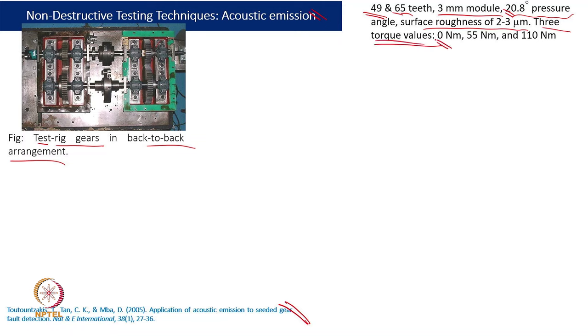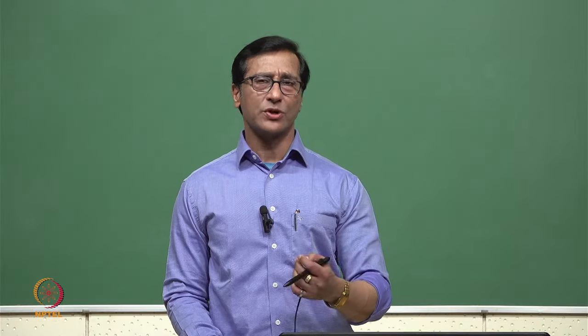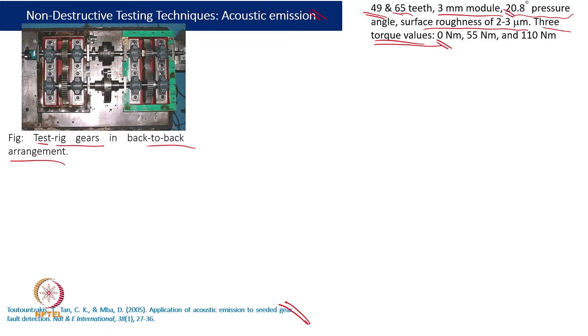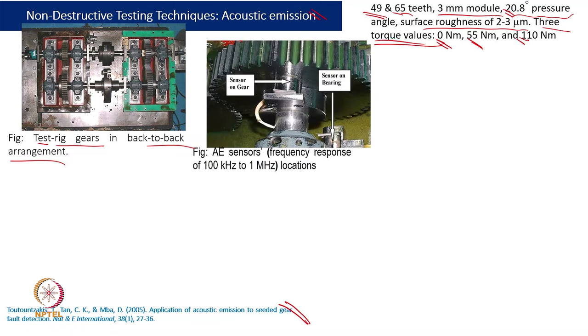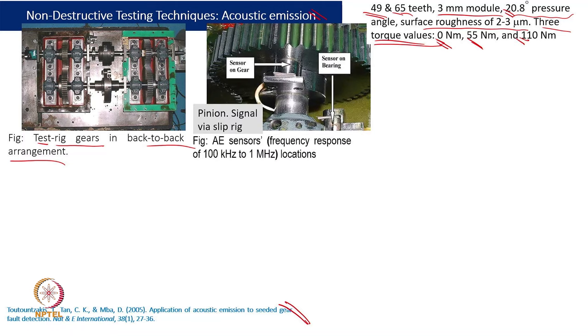In one case, almost 0 Newton meter. Of course, it cannot be absolutely 0, because they need to rotate the shaft. Naturally, there will be some torque, but it is negligible, and every time it will be deducted. So, we can treat this as 0 Newton meter. Next one is 55 Newton meter, and another one is 110 Newton meter. And this is what they have shown, that they tried to capture the signal using two acoustic sensors. One sensor was directly fixed on the gear, the other sensor on the bearing housing.